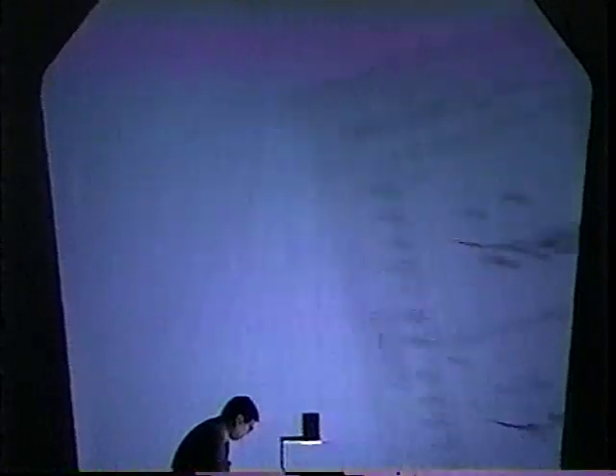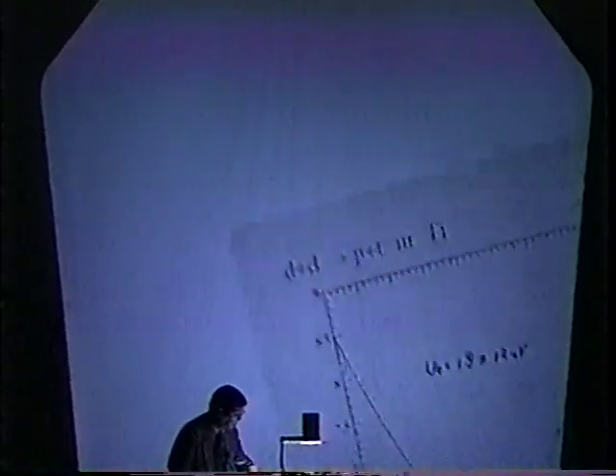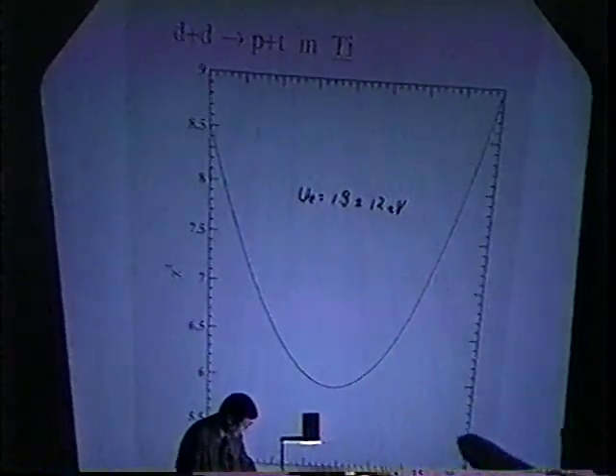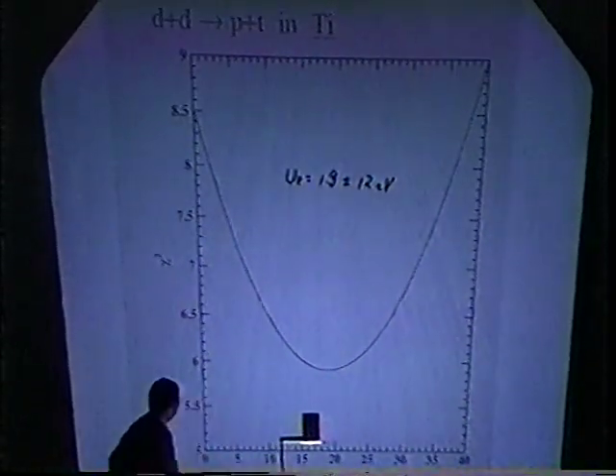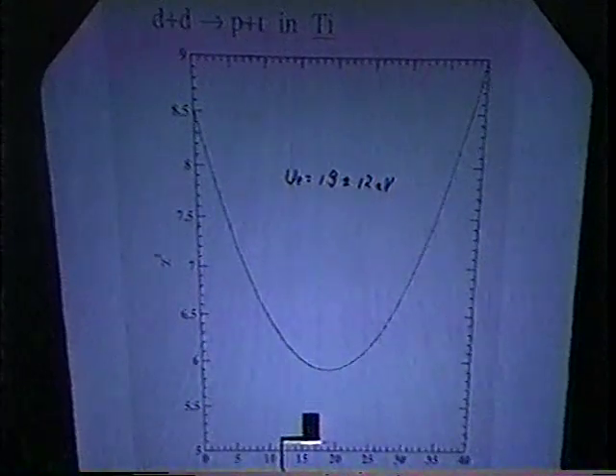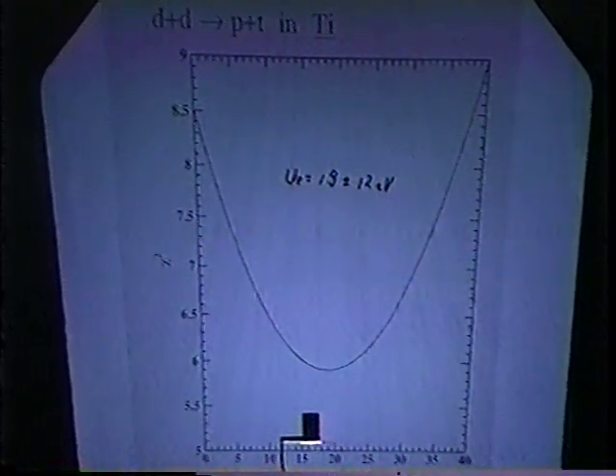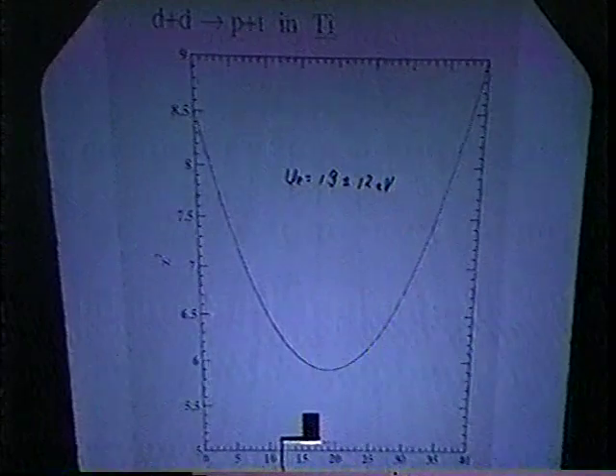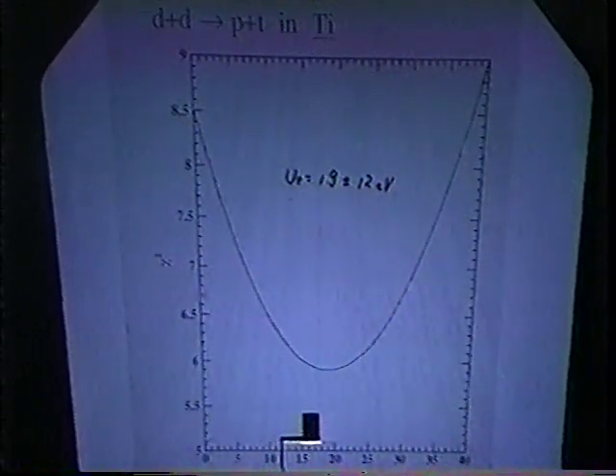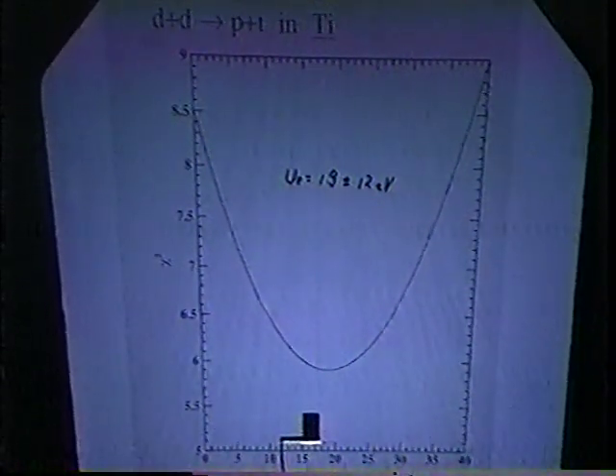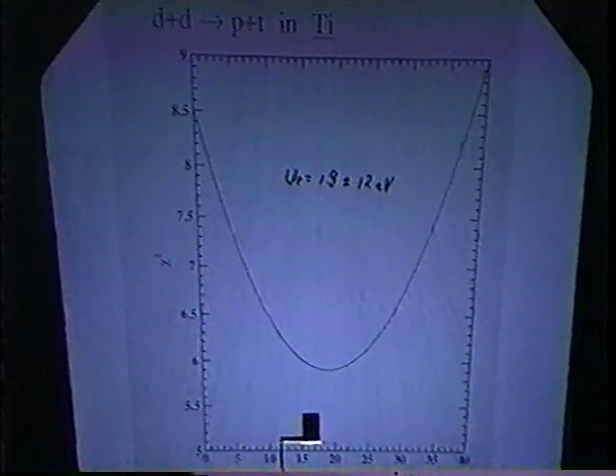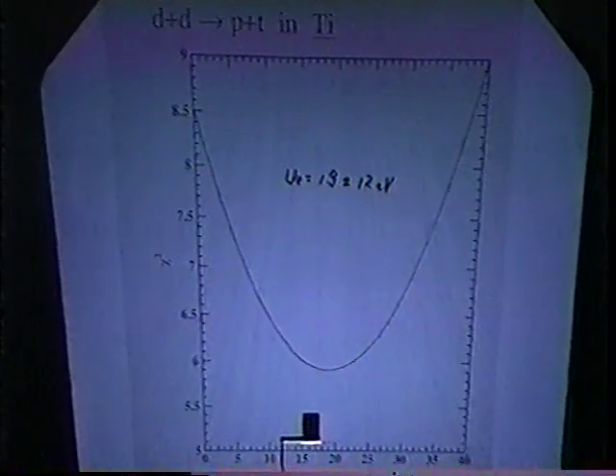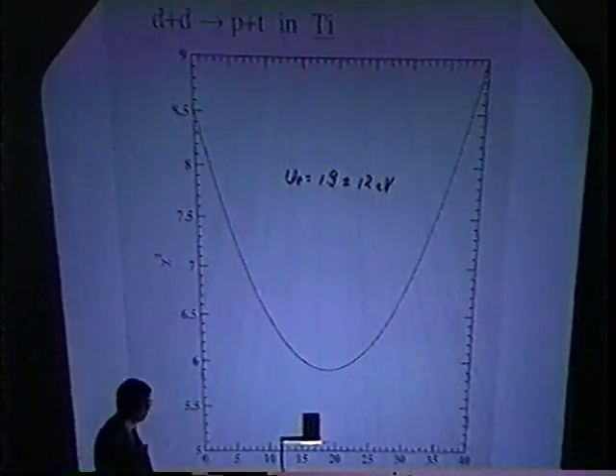And of course, in order to check whether this enhancement really has meaning or not, we proceed with the chi-square test for the data which I just showed. And the chi-square tells us that our screening potential is something like 19 plus minus 12 electron volt within this energy region.